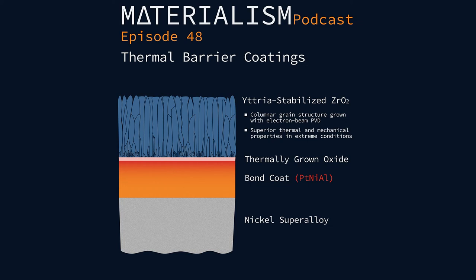The bond coat wants to get longer. It's trying to expand. Another way to think about what's causing the stress is actually inside the material itself. Let's say your bond coat was made of a pretty common one, nickel, platinum, aluminum. As you're losing the aluminum, it's switching from one crystal structure to another. You're switching from the nickel aluminum crystal structure, a one-to-one mixture basically, all the way over to Ni3Al, something where it's lost a bunch of aluminum, obviously, because you're losing the aluminum. And there's a volume change. It's shrinking. So there are multiple reasons that explain this evolution of strain, causing this undulation to match the strain that's happening in there.